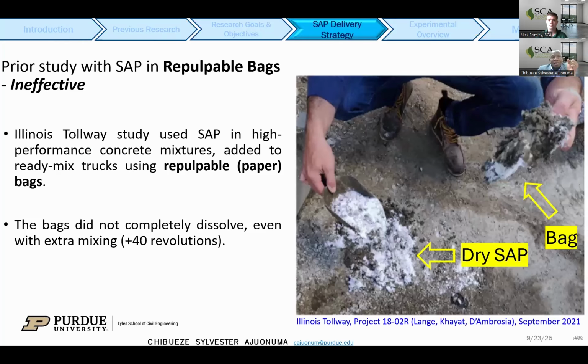I also want to emphasize on this. One of the studies, in terms of objective 2, the effective way to deliver SAP in concrete, is one where they tried to add SAP for commercial, large-scale application. They used repulpable bags, but it was ineffective. As you can see here, at the end of the day, even after mixing 40-plus revolutions in a concrete mixer, they found out that there was still dry SAP there, and the bag did not dissolve.